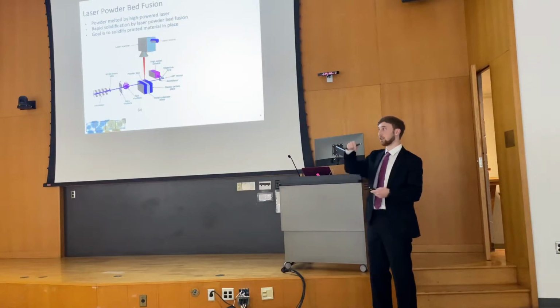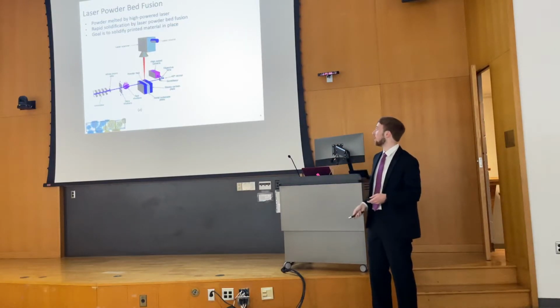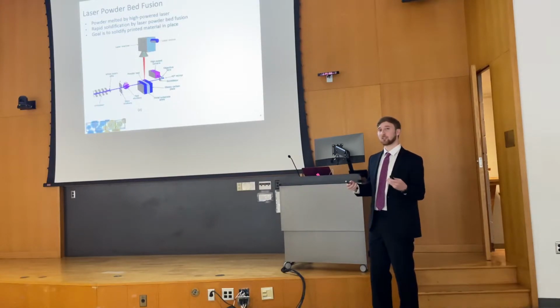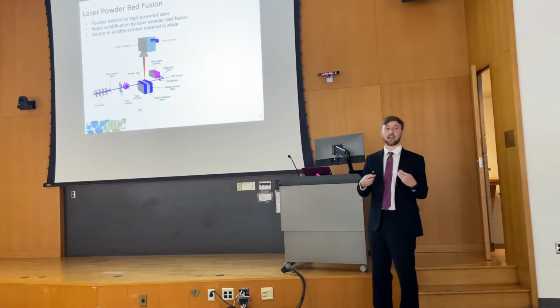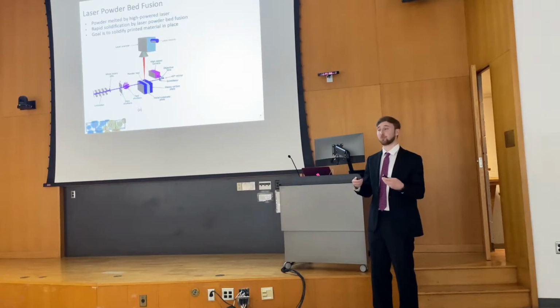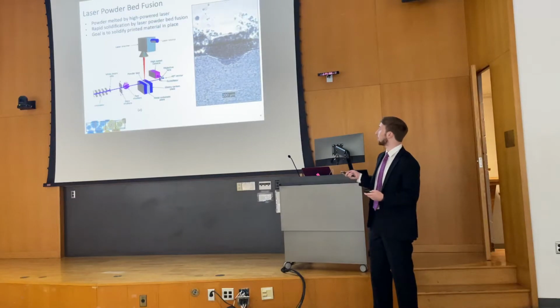The trials we did were in one spot, which was spot welding, or across a single layer line scan. As you can see, it was a system much like this, where you would have a powder bed and a metal substrate and the laser up there. Now, to characterize this, you would often characterize it after the fact and compare that to your parameters for future experiments. We wanted to study it in situ, so we used a high-speed synchrotron source, which had a high-speed camera at the other end to give us an idea of what was happening inside the melt pool.